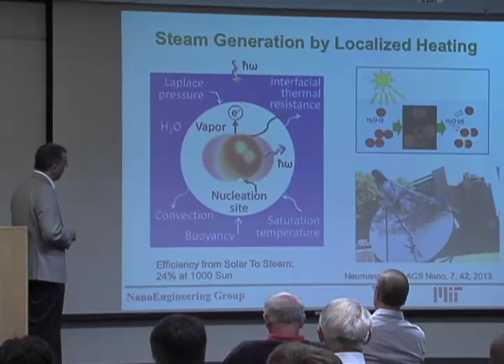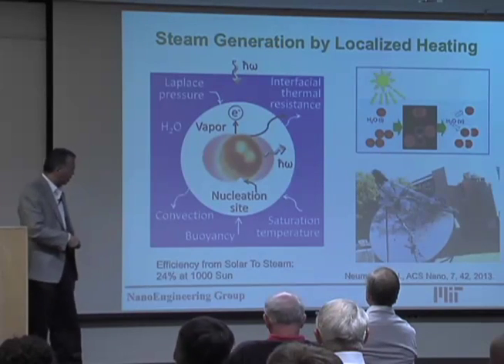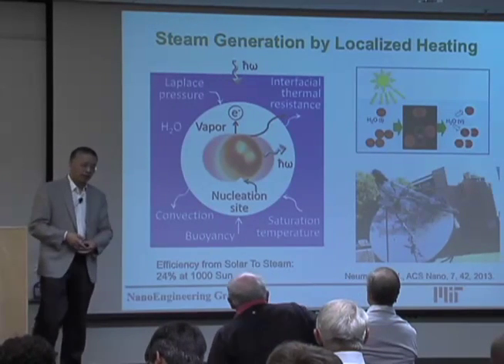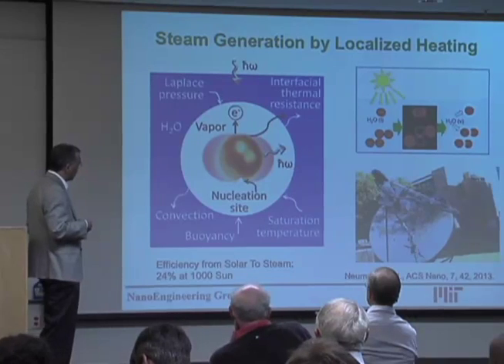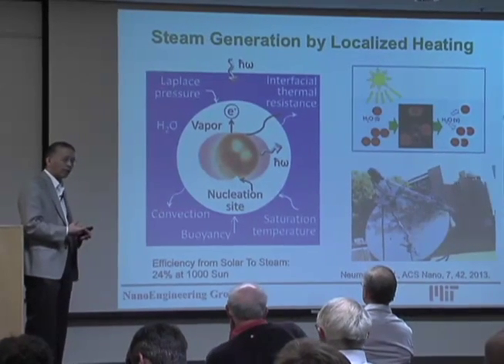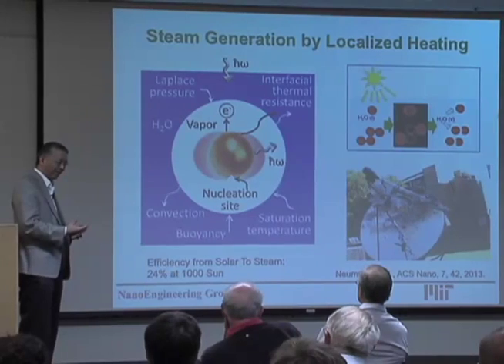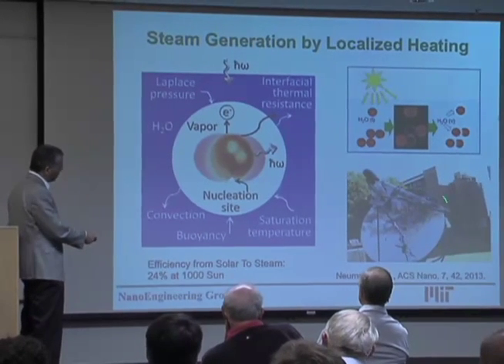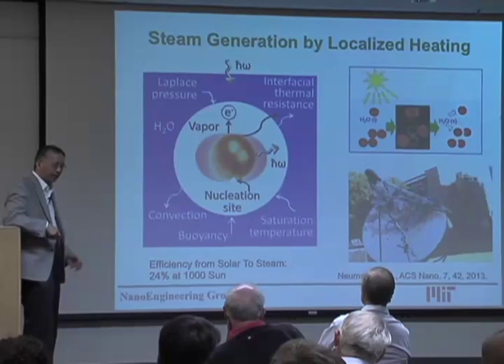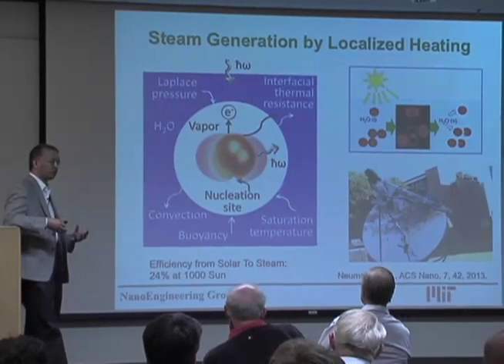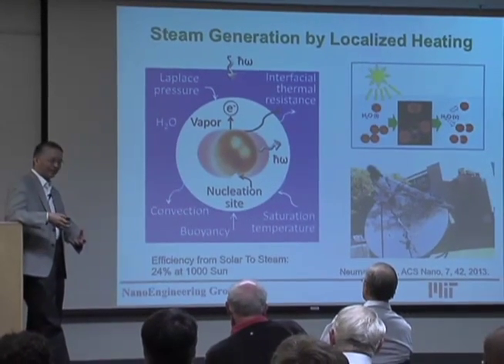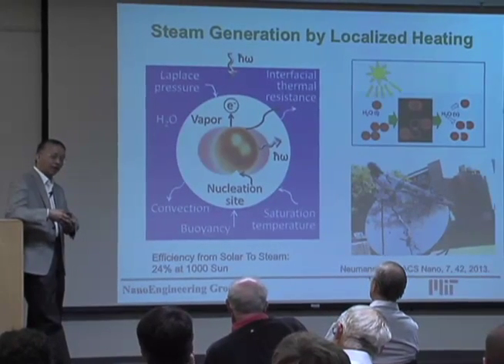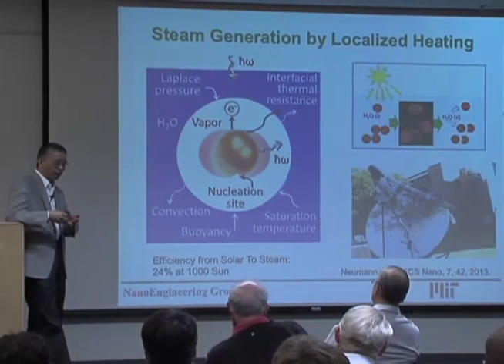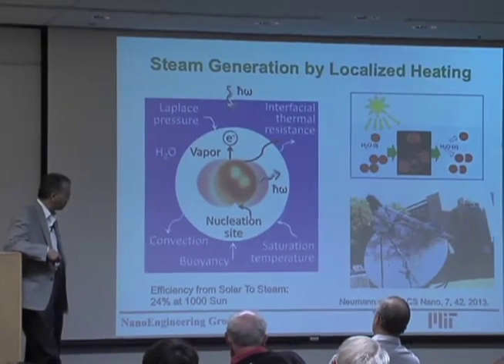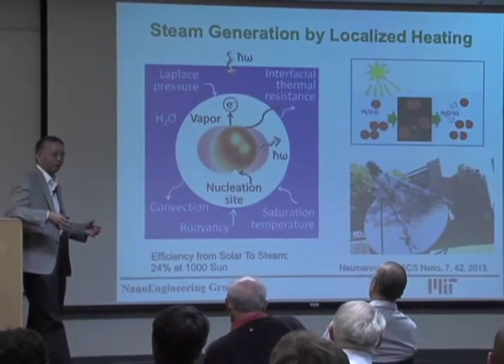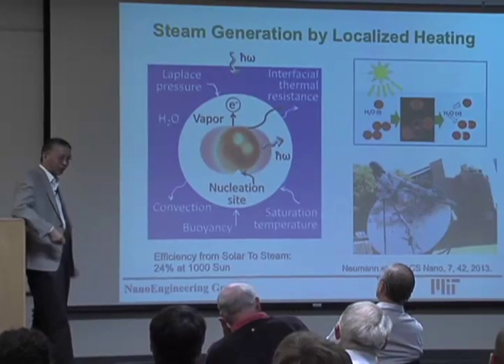Last year there was an interesting study by the Rice group, Naomi Halas. What they did is they put nanoparticles into water and used concentrated sunlight, and they demonstrated that they can generate steam even when the surrounding is ice. So this is localized heating, and it drew a lot of attention. Their first paper was published in ACS Nano, and it was the most downloaded paper for many months.